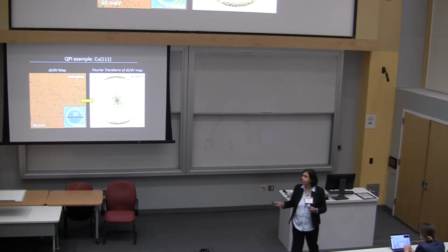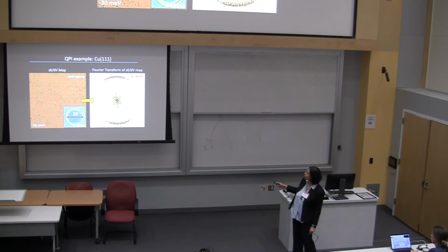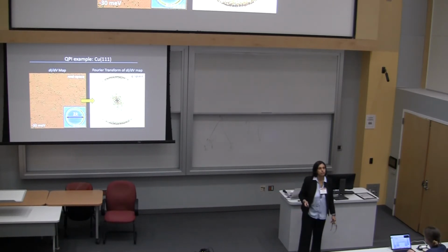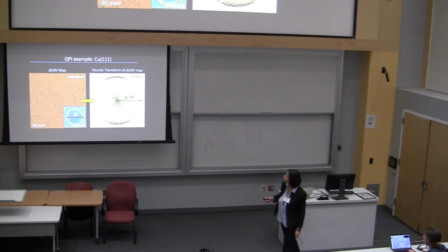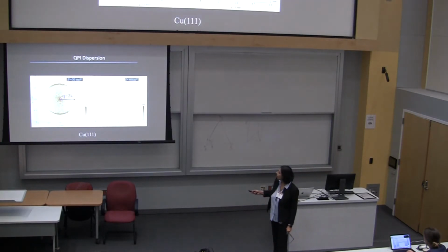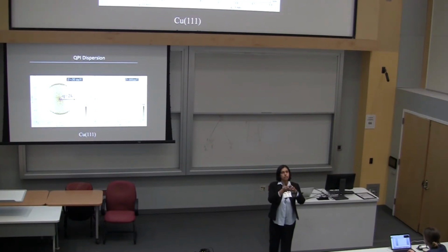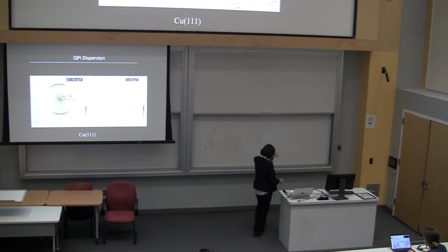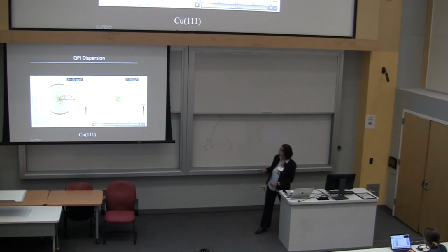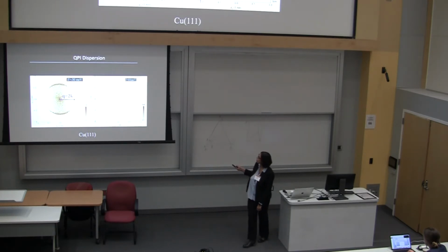If you take a Fourier transform of this image, you get this circle which represents all the scattering vectors in this image, okay? And you can do this as a function of energy. Let's say we start from the bottom of the band where the circle is small, and we go to higher energies. You will see an ever-expanding circle, and that's your dispersion.